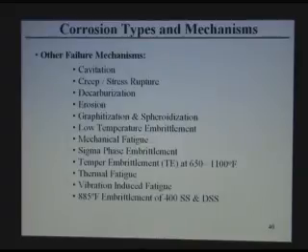Thermal fatigue, it is again if you have a lot of cycles of heat and cool, this causes fatigue. Vibration also can cause fatigue. And the 885-degree embrittlement of these chrome steels and duplex steels can happen, they become brittle. Some phase forms and makes it brittle. That's why we cannot use duplex above 600.